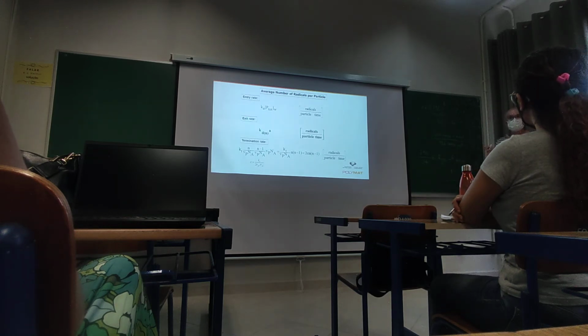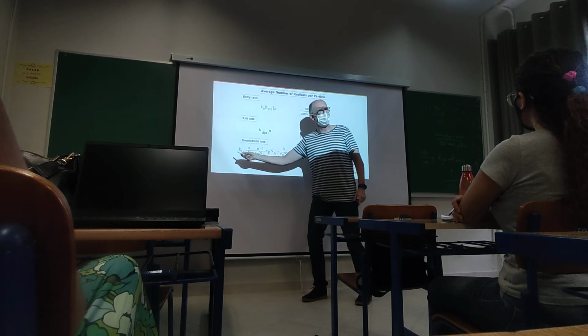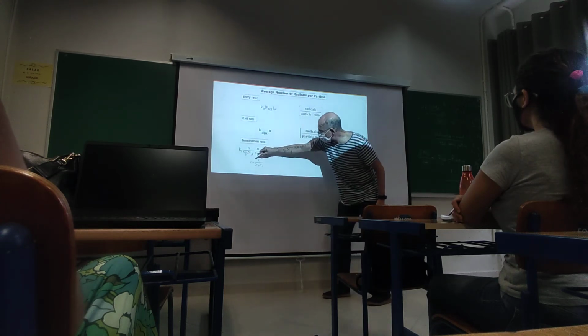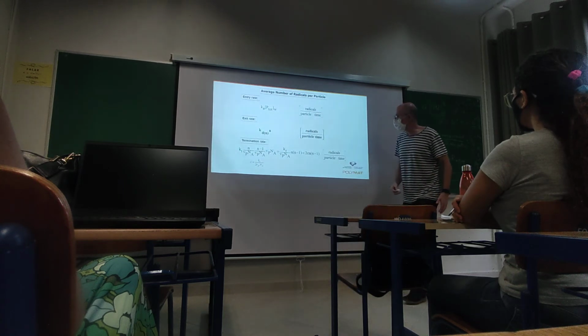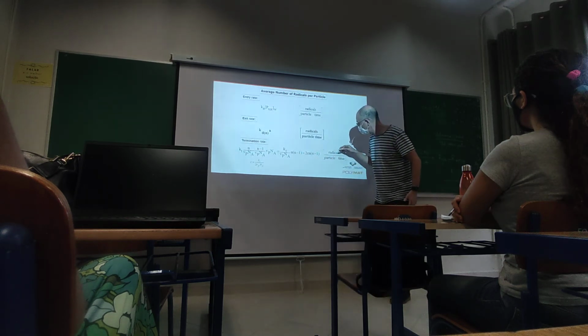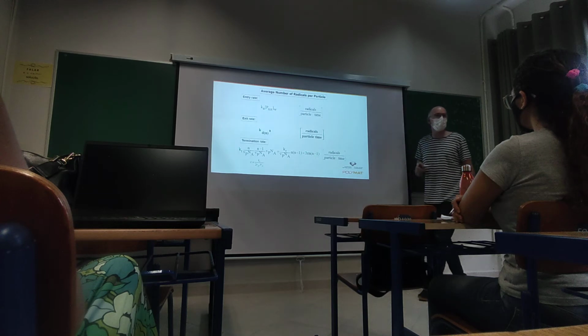But in emulsion polymerization, this has a strong impact. So that's why we have to do this calculation here. And then this is substituted by this c, which is used in emulsion polymerization to indicate termination. Therefore, the rate of termination in frequency units is 2c times n times n minus 1.